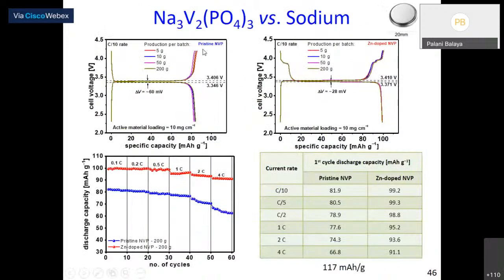Now I'm comparing this pristine NVP versus zinc doped NVP against sodium. This is also called a half cell. You know half cell. So as you can see here, 5 gram or 200 gram or even 3 kilogram, the discharge capacity doesn't vary significantly. These are the pristine NVP versus sodium. So typically we get about 82 milliampere hour per gram at low C rate, and at high C rate 67 milliampere hour per gram.